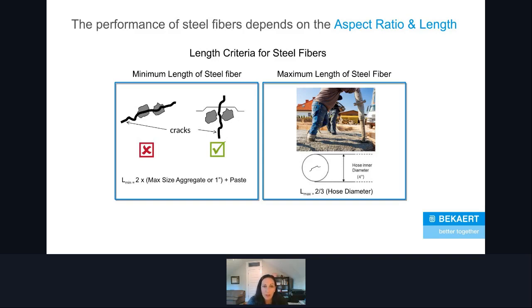And those tend to have a max aggregate size of about 3/4 of an inch to maybe an inch, inch and a quarter, somewhere in that ballpark. For that, we would use a 60 millimeter fiber, which is about 2.4 inches long. And the reason for this is because you want to achieve compatibility between the fiber length and the aggregate size that's being used, because the cracks are going to tend to form in the paste between the aggregates, right? We're talking normal Portland cement concrete here, not UHPC.